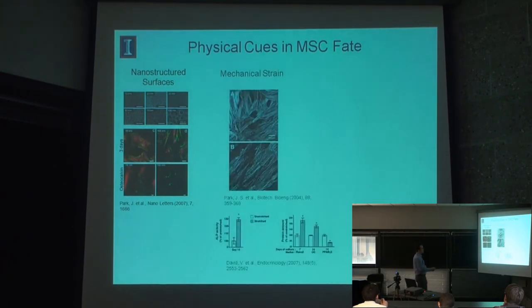Similarly, you can do similar studies with strain. And so here's showing some mesenchymal stem cells that are being stretched on a polymeric substrate. And by doing this, you can see a differential regulation of genes associated with different differentiation outcomes. So here we have alkaline phosphatase activity in cells that were stretched for a period of time have higher levels of bone cell differentiation, and that's true for several other markers, while they see a decrease in genes associated with fat. And so what a lot of these studies are pointing to is that cytoskeletal tension appears to be something that's important for bone cell differentiation.